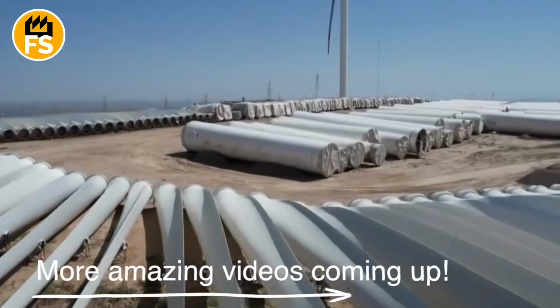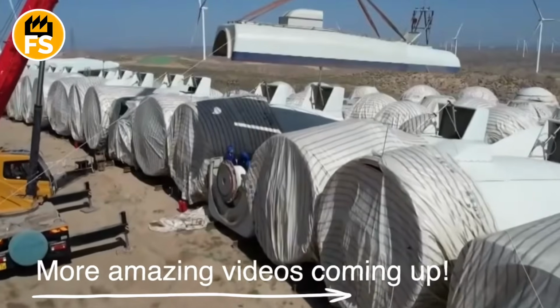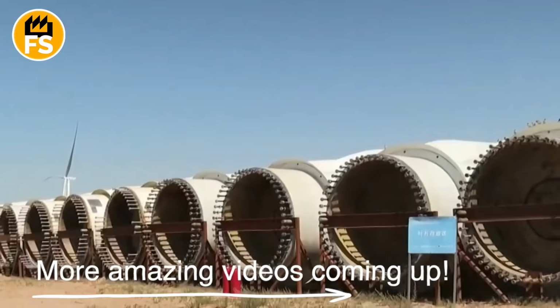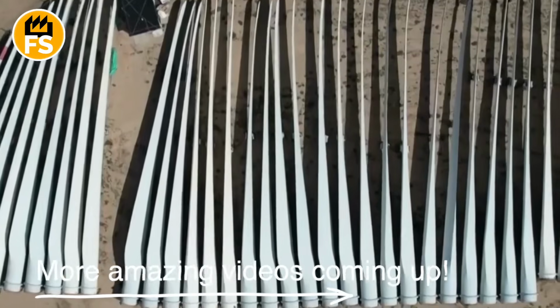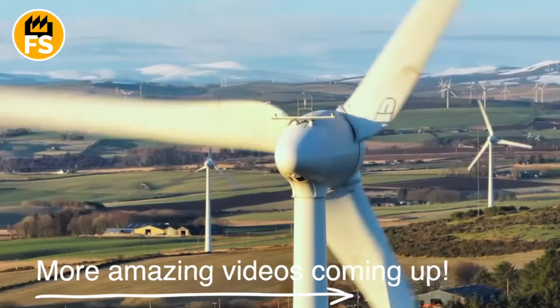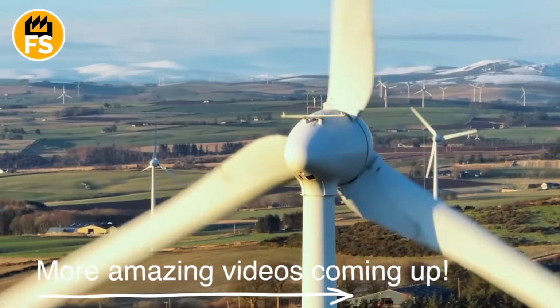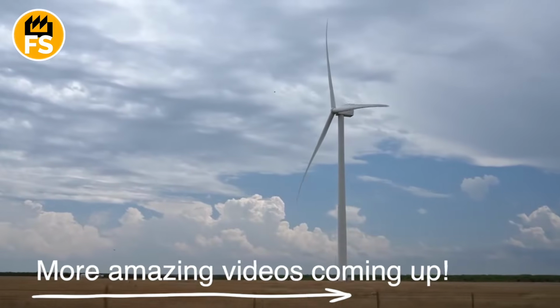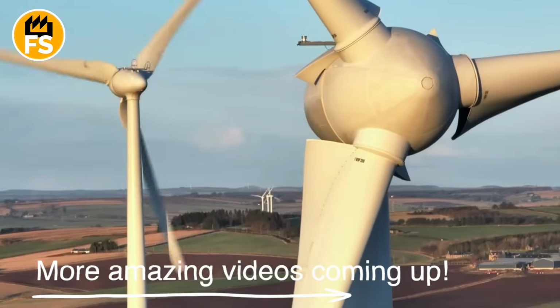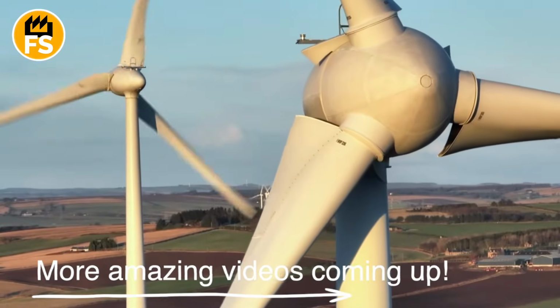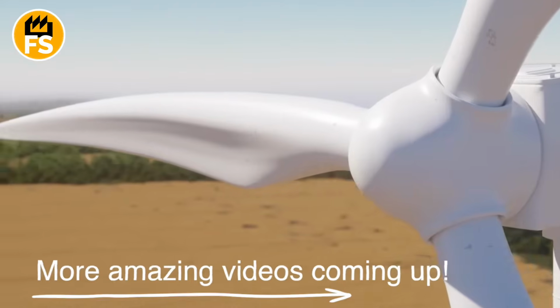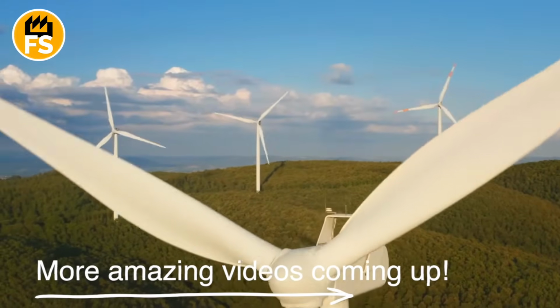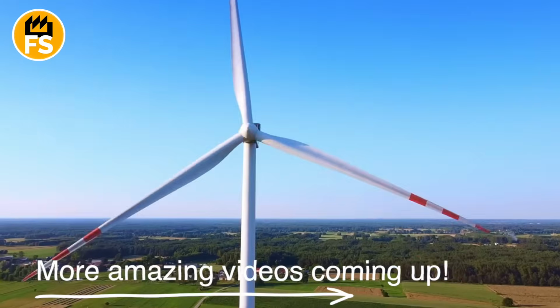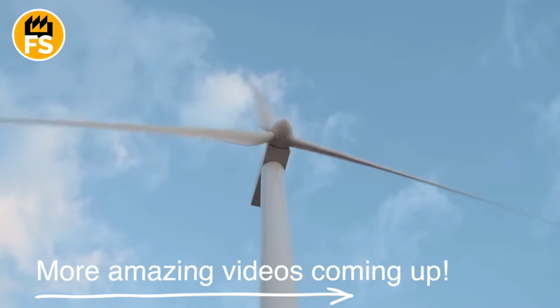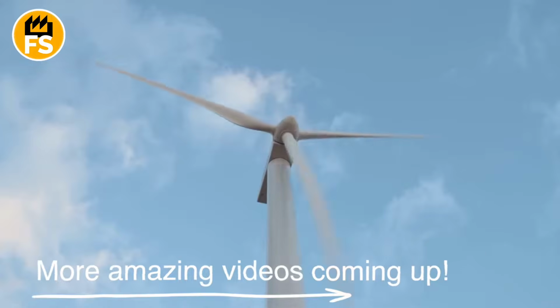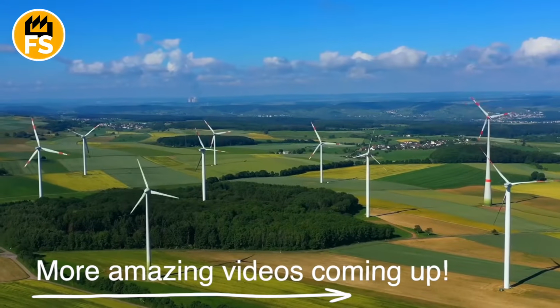Due to their volume and composite material, fiberglass that doesn't decompose, they can occupy significant areas, becoming museums of green energy. The tips of the longest blades can reach rotational speeds of 180 miles per hour. Though they don't exceed the speed of sound, this requires the blade tip to be perfectly designed and protected from erosion. An ordinary raindrop hitting the blade at such speed has destructive force similar to sandblasting. This forces manufacturers to develop high-tech but expensive protective coatings for blade leading edges.